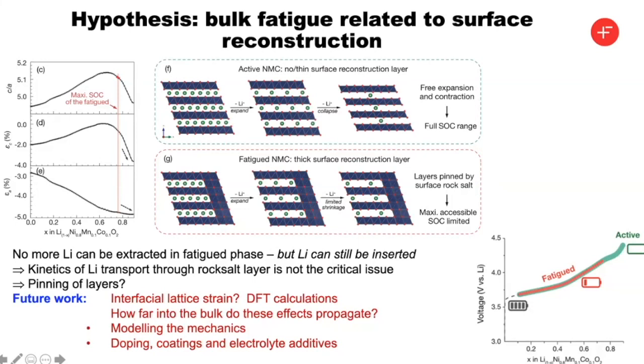charge. And so we can calculate the strain in the C direction and the A direction, so in this direction versus the layer spacing, and you can see that the fatigue phase basically stops when this strain has been minimized in the C parameter. So we're going to at least hypothesize that the rock salts are helping to pin these layers apart, and that's making it very difficult to pull the residual lithiums out.